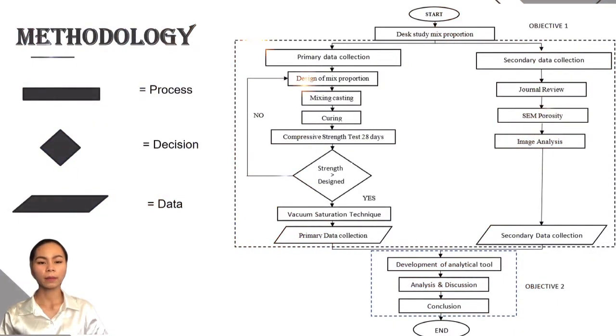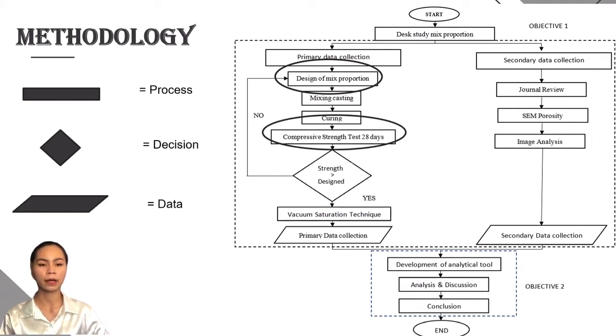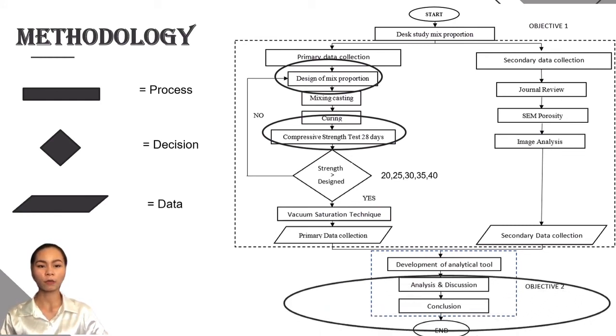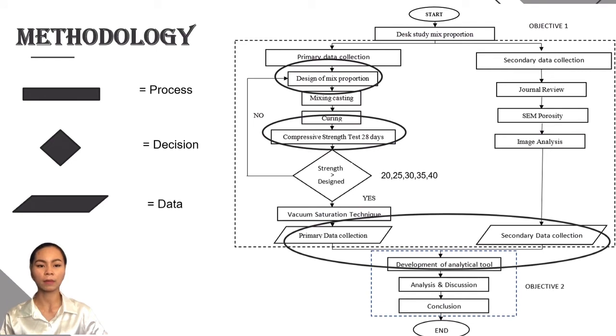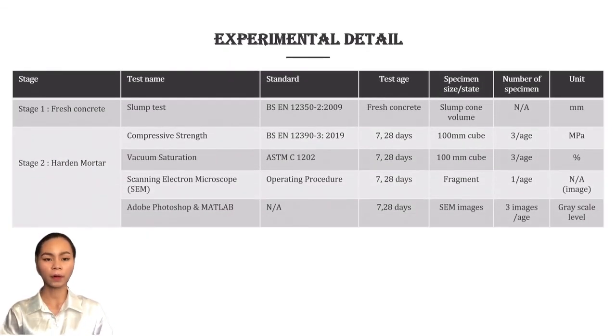To get the primary data for this project, firstly, I will design the mix proportion of concrete and cure it for 7 and 28 days. Before the vacuum saturation is done, the concrete will be tested for its compressive strength first to achieve the scope of concrete design in this project, namely 20, 25, 30, 35, and 40. The result from vacuum saturation will be compared with the result from image analysis of SEM to achieve the second sub-objective of this study. There are two stages of experiment for this project.